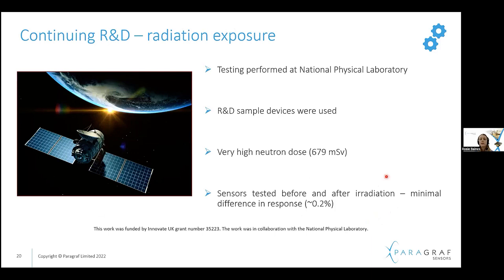So I'll just touch briefly on another extreme environment. Radiation exposure is something that we have done some testing on at NPL, again using R&D sample devices and exposing those to a very high neutron dose. So using 679 millisieverts. Just as a comparison, that's like 6,000 or 7,000 chest X-rays in that dose. So quite a high dose, and the sensors were then tested before and afterwards, and showed a minimal difference in their response, around 0.2%, which is a really promising result and just helps to show the general robustness of the material and of the device as well.